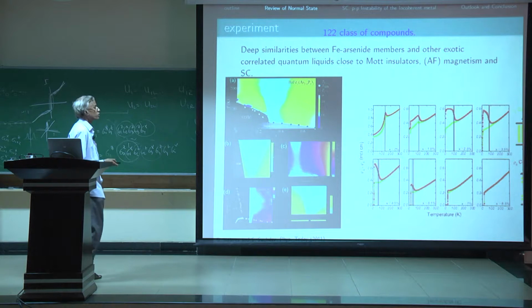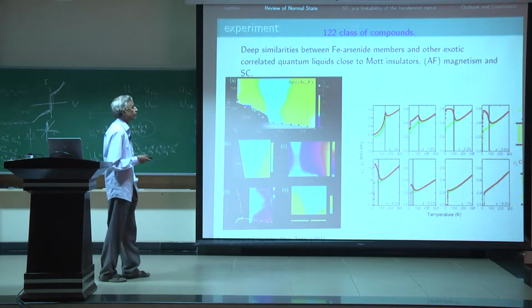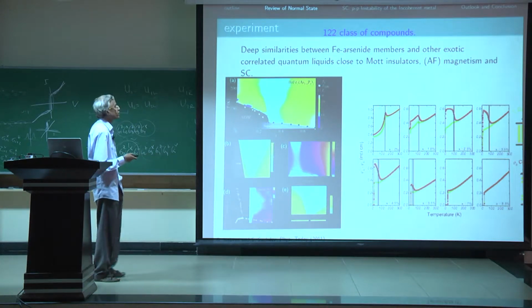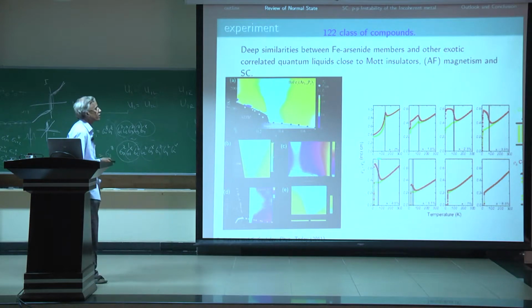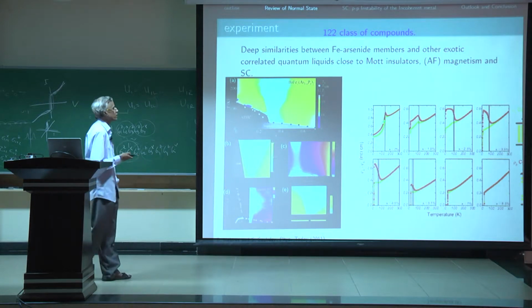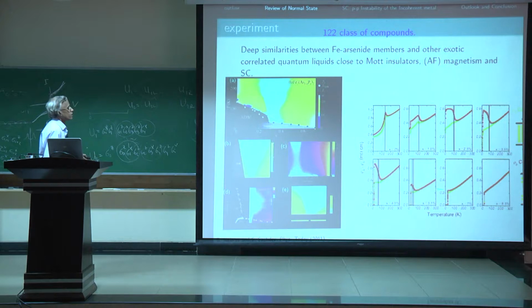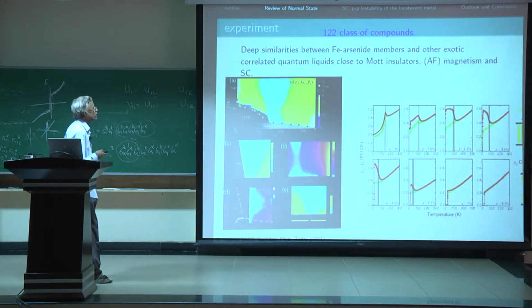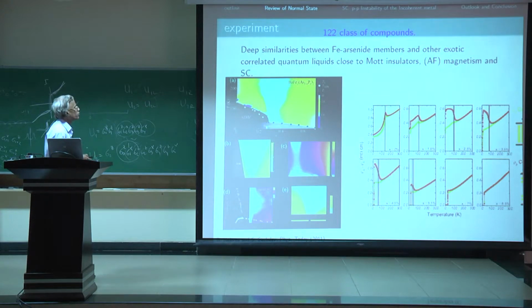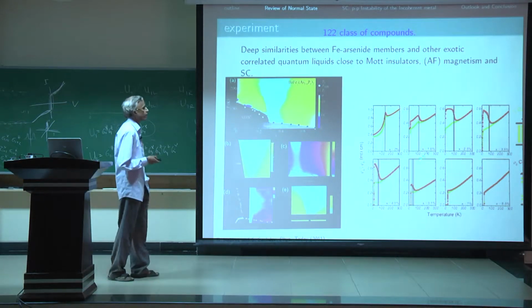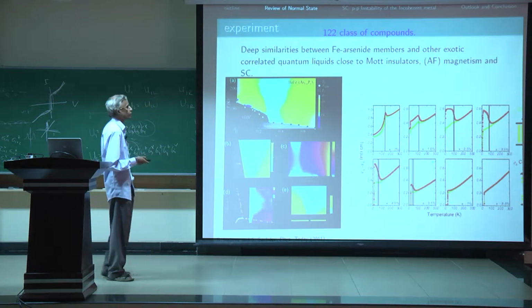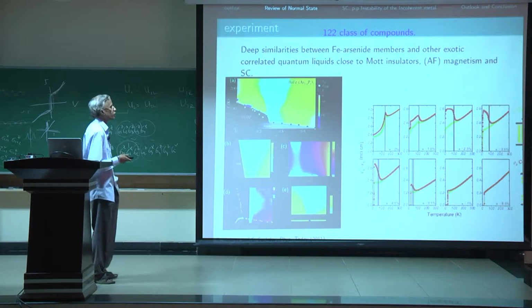So what I want to focus on is also the data which was first done by Ian Fisher and company for this material, and Sitikanta Das and Suchitra Sebastian have redone this for the strontium compound, in which case the tetragonal orthorhombic distortion and the antiferromagnetic transition occur simultaneously, in contrast to what happens in Ba-122. However, the resistivity data are very similar to what Fisher and company observe.